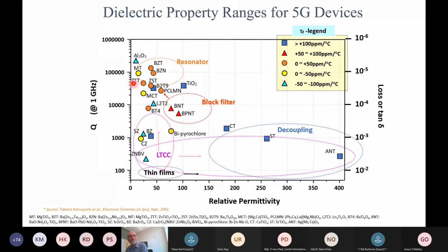And what's also interesting about this plot is we see that there's a general trend, right? As we increase the permittivity, the loss goes up or Q goes down. And we can see this trend, and it's fundamentally related to the polarization mechanisms that give you these properties. So if you have a larger polarization that gives you the higher permittivity, it will naturally cause loss in these frequency ranges. So there are trade-offs between these properties. Just one other point here is these materials have been grouped to be within certain ranges of temperature coefficient. So that was the third variable I talked about. And these are very low dependence of permittivity on the temperature, which is very important.